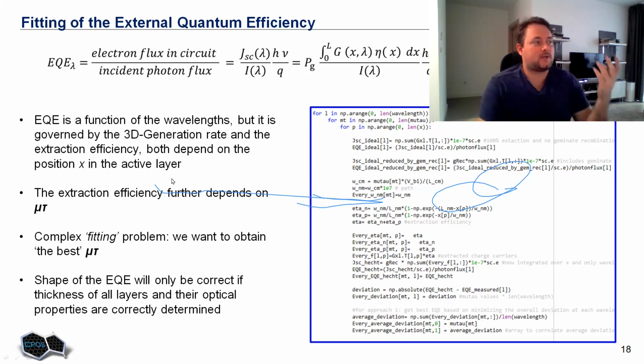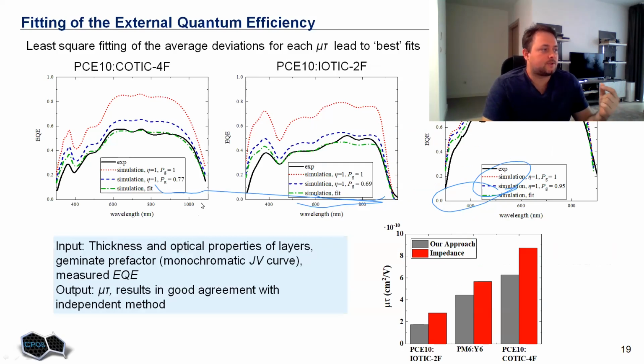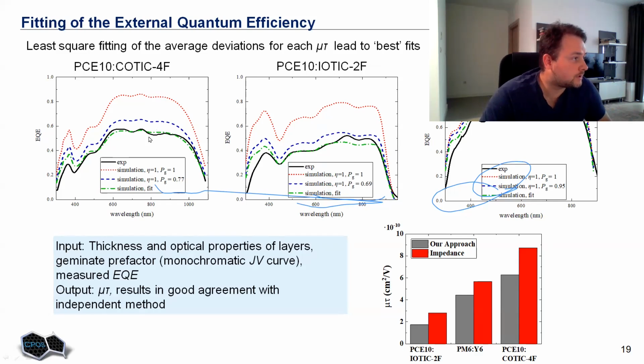So then we have experimentally measured quantum efficiency and calculated quantum efficiency as a result of the synergy of numerical and analytical models, which are embedded in this equation. Then this mu tau would be considered as a single fitting parameter for fitting the experimental EQE. Let's say we don't know this mu tau product because it really depends on morphology, on the materials which we use, on processing conditions, and that is very important information in order to quantify extraction and recombination losses in these devices.